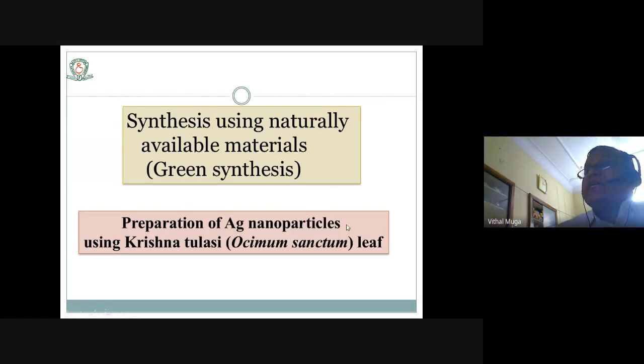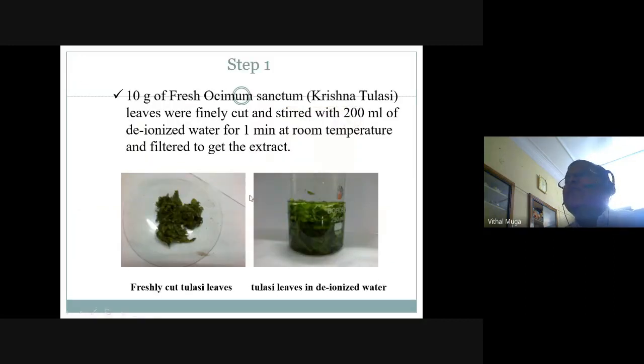Now, preparation of Ag nanoparticles using tulasi leaves. Tulasi leaves we are very much familiar with. Every day we may do some puja also, and what is important is that I have given 4 steps. Take 10 grams of fresh tulasi leaves, wash them and cut into pieces, and then take about 200 ml of distilled or deionized water, and stir it for about 1 minute at room temperature. I said 1 minute, but it is better to stir for 5 minutes.